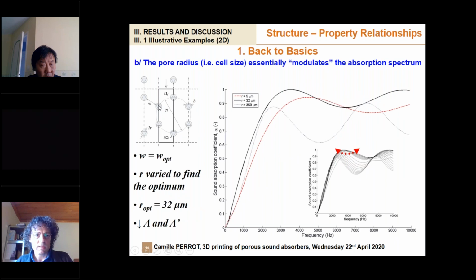Then you can keep this throat size as a constant size, the one which had been found previously in the range of, let's say, intermediate resistivities corresponding to a strong sound absorption level. And what we saw is that you have a kind of modulation of the sound absorption level, which means that eventually you can tackle some specific parts of the sound absorbing spectrum, but this is less impacting when compared to the throat size.